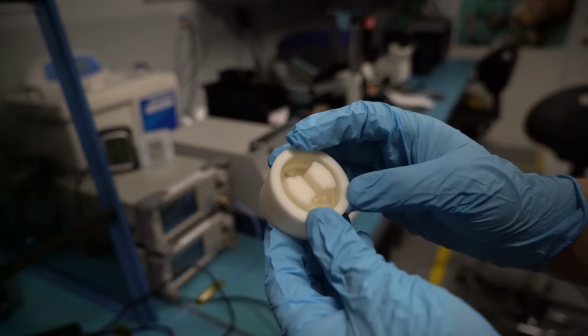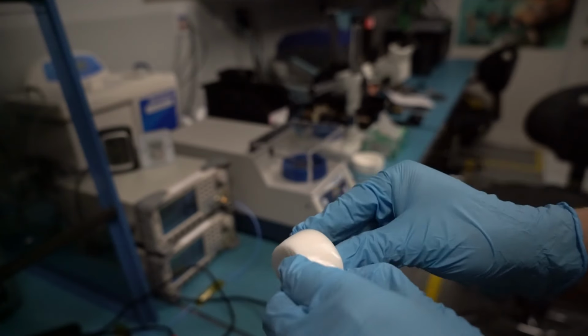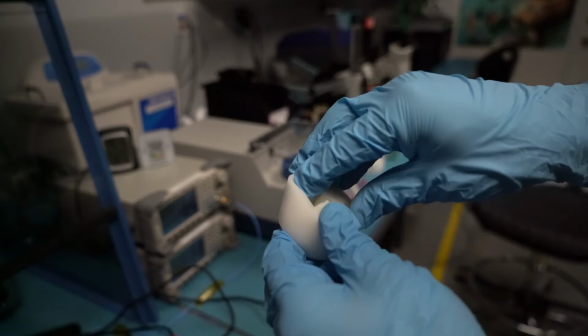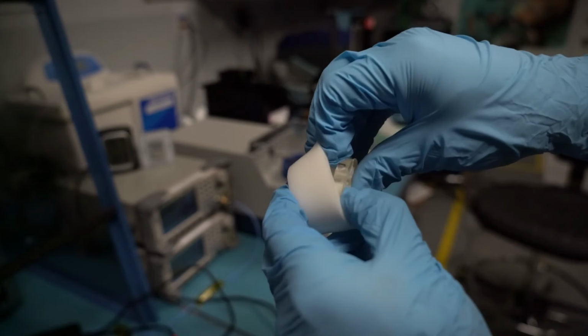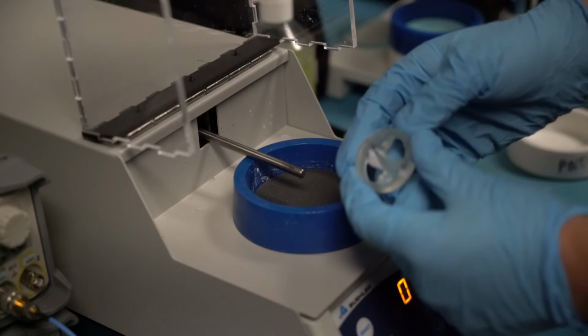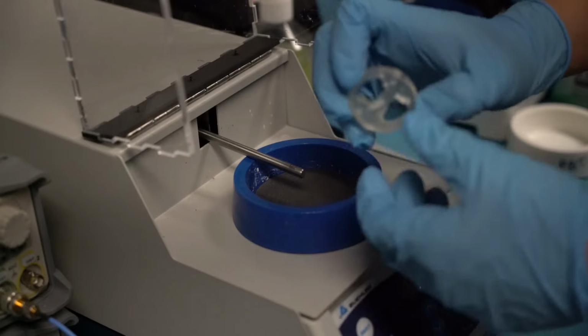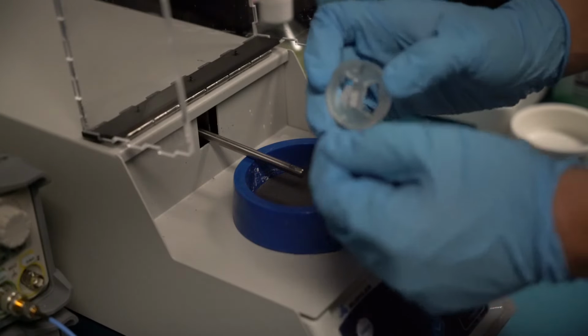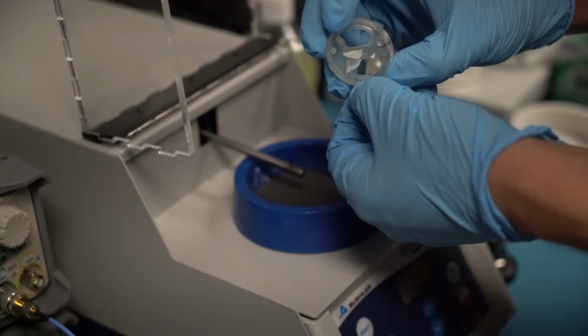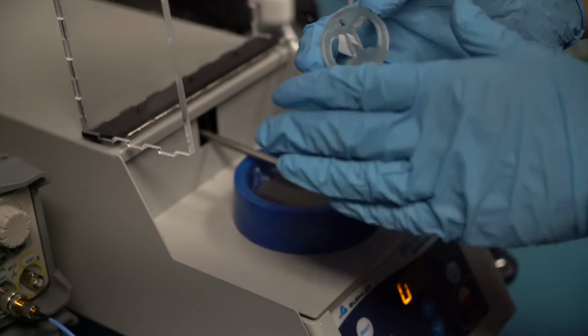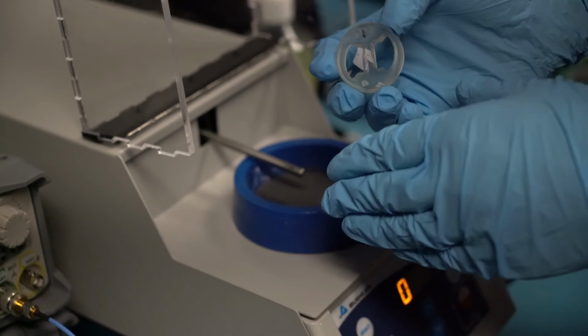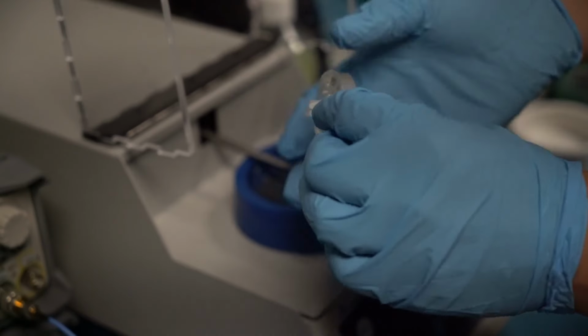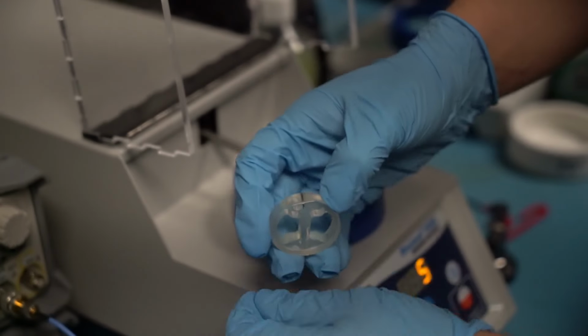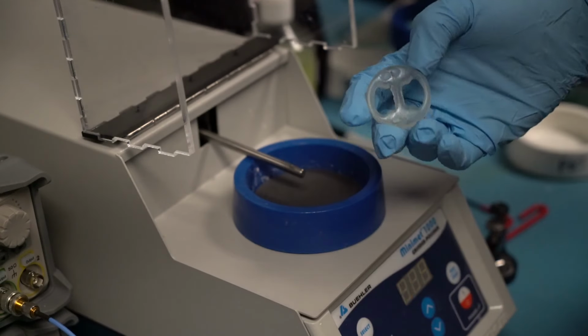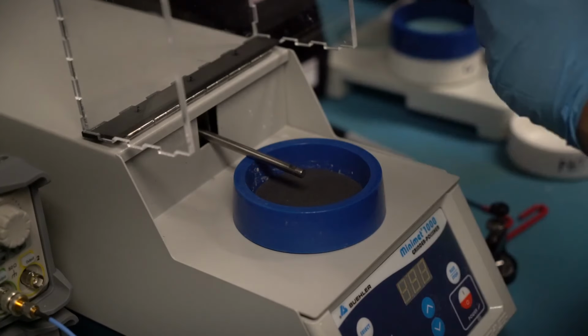And now it's been about 15 minutes and the sample has cured, so I'm going to remove it from the mold. And we can see that there's a little bit of a meniscus along the perimeter, as well as a couple of sections sticking up near the center where it looks like some of the resin had stuck to the side of the mold as it was poured in. So now I'm going to peel off a little bit of the loose stuff that comes off by hand, and then prepare to polish off the rest.